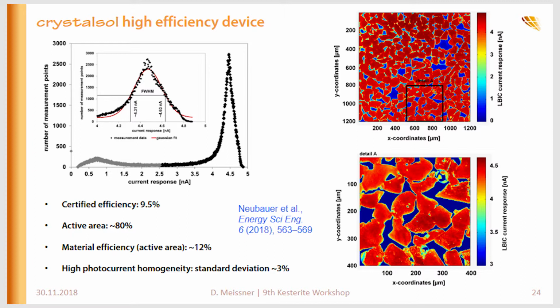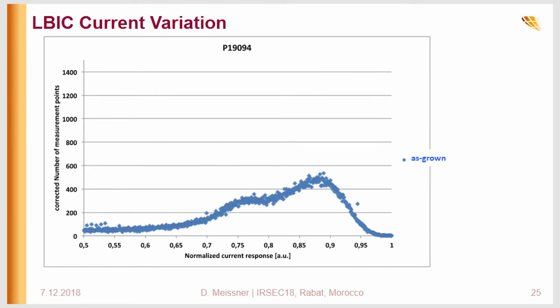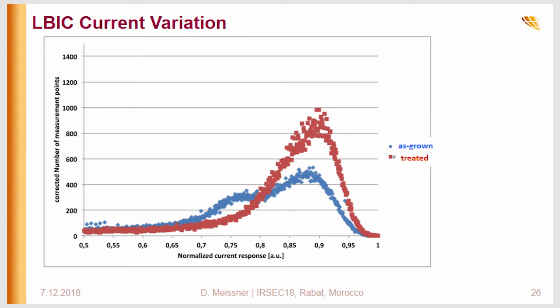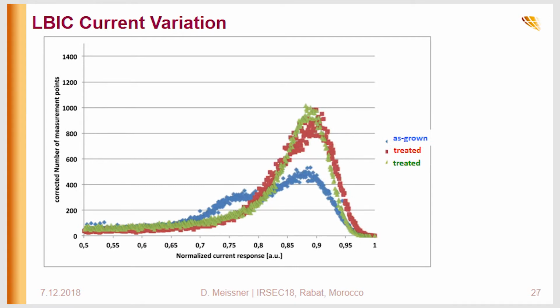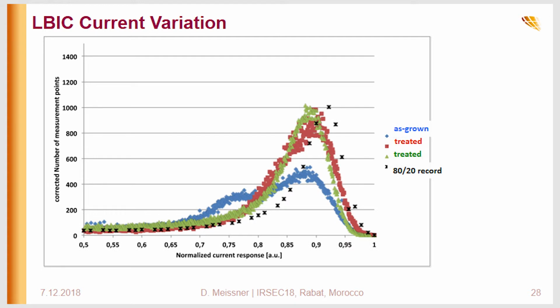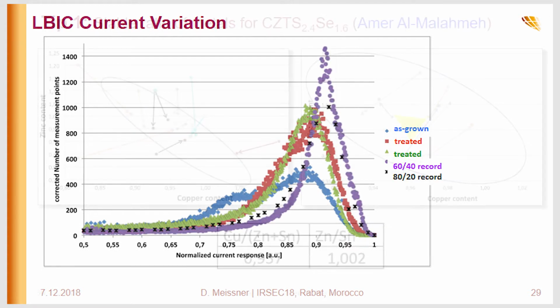So we know that the quality of the powder crystals is within plus minus 3%. So it's very homogeneous. But to achieve this homogeneity, you have to do a few tricks, which I cannot tell you. So this shows this current distribution for different cells. And you can see the record cells finally have the most narrow distribution of this current behavior.